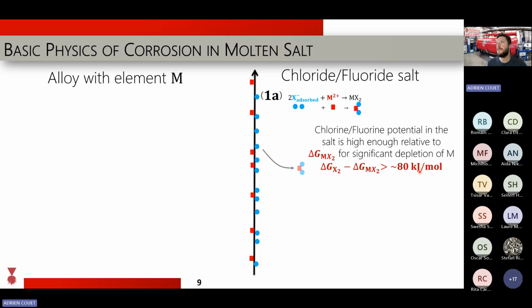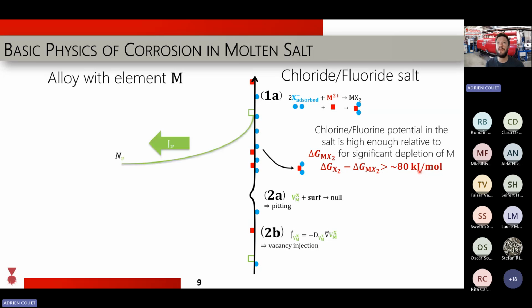How that happens usually is that you have those ions in the salt that are going to react with your material to form those metal chlorides, and since they are now dissolving, you're going to form vacancies at the interface. Those vacancies can disappear by either surface roughness, so you increase the surface area and the surface energy of your material, or you inject vacancies. And if you inject vacancies in the material, then that means you have chemical transport, right? The vacancies are going to diffuse via atoms, and those atoms are going to diffuse in the opposite direction of the vacancies, and you're going to end up with a depletion profile of your alloying element M in your system.